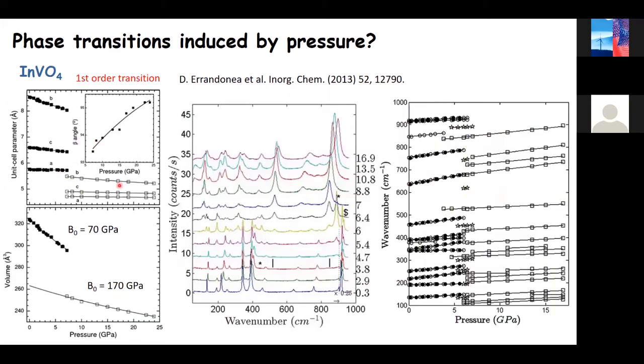From the experiments, we obtained information on what happened with the unit cell parameters. You can see here clearly that this axis is much more compressible than the other two. So compression is anisotropic, as I commented before. It is also anisotropic for the high pressure phase. However, we see two important things.